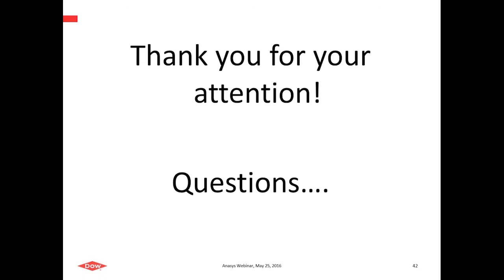So there's a question about what type of substrates do you recommend? So Greg, can you comment on the substrates you typically use for your measurements? Yeah, we've been using something like gold-coated quartz, which is a gold mirror basically, zinc selenide, zinc sulfide, IR transparent supports, and those are common ones that we would use. Yeah, and in general you want a substrate that is either IR transmissive or IR reflective but not IR absorptive.